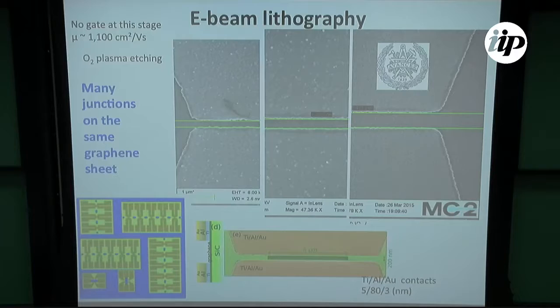They are 300 nanometers long, or 200 nanometers long, or up to 600. However, 600 nanometers long do not conduct Josephson current. And they are 4 micrometers wide, usually, and then graphene extends further down under the aluminum contact.